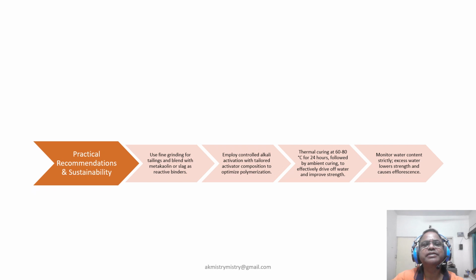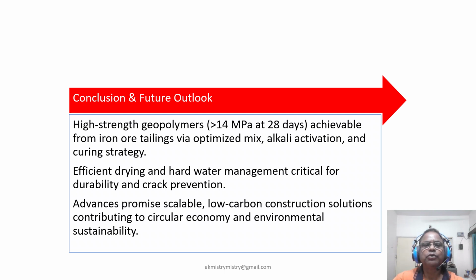Together these measures support sustainable construction practices and circular use of mining waste. In conclusion, we can say that high strength geopolymer with compressive strength above 14 MPa at 28 days can be achieved with iron ore tailing, provided we optimize mix design, carefully select activators and implement a stepwise curing strategy. The key enabler is efficient water management, driving off excess moisture while preventing microcracking to ensure durability. By also addressing challenges such as hard water, we can create a scalable solution that replaces the traditional cement system.